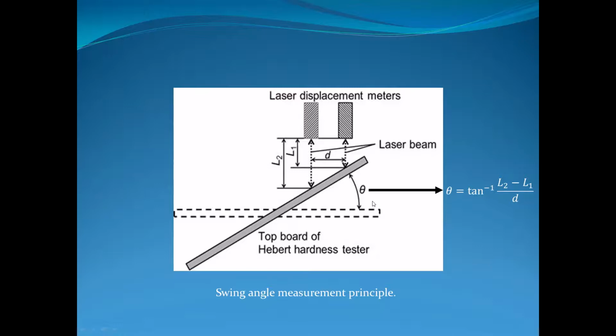The swing angle theta can be expressed by this equation. D is the horizontal distance between the laser displacement meters, and L1 and L2 are the vertical distances between the tester and the laser displacement meters. The angle theta can be precisely measured, and the measurement parameters D, L1 and L2 do not depend on the method of installation. The test specimens used are standard test blocks for Brinell hardness from 100 to 600 in steps of 50.